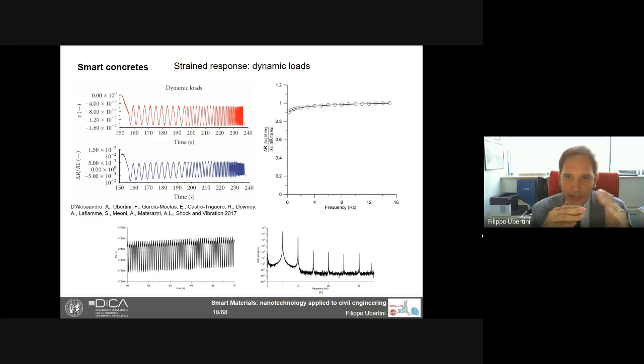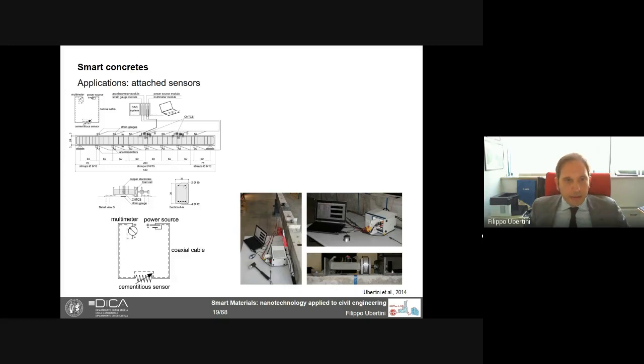Linear would be that we have a frequency response function that is flat, equal to 1, while here we have a frequency response function that is a little bit increasing in frequency, which means that we have more sensitivity at higher mechanical frequency compared to the sensitivity we have at lower mechanical frequencies. Another notable aspect of these sensors is that the response to a harmonic mechanical load is periodic, but it's not harmonic. It has superharmonic components, as you see in the bottom right diagram of this slide. This, of course, is a drawback of these sensors that we will discuss later on.